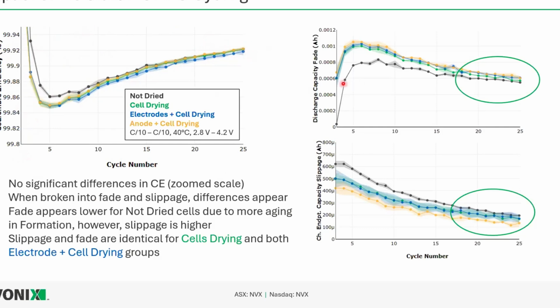But when we split this up, we can actually see there are differences between these groups. These not dried cells actually have lower capacity fade. This is likely due to forming more SEI. We saw that they had a lower first cycle efficiency, so more lithium went into forming a thicker or robust SEI on the anode surface. So maybe this makes sense that this capacity fade is a bit lower. So why was its Coulombic efficiency the same as these other cells?